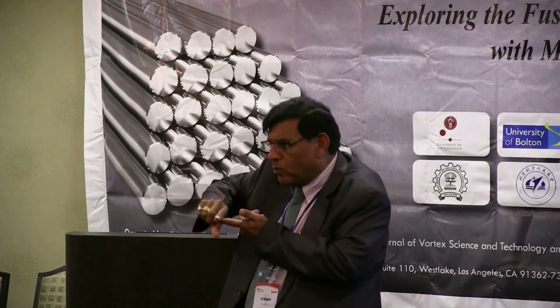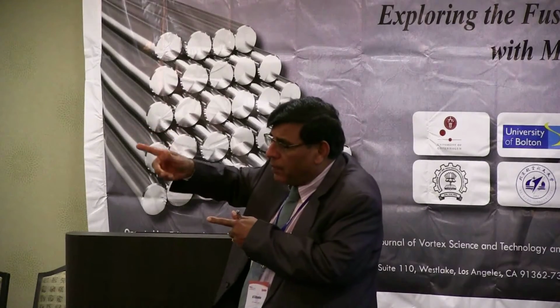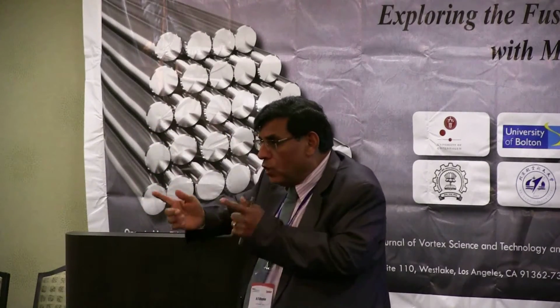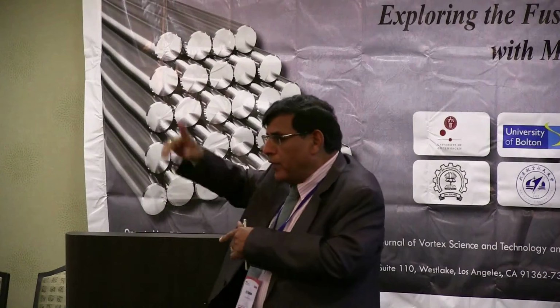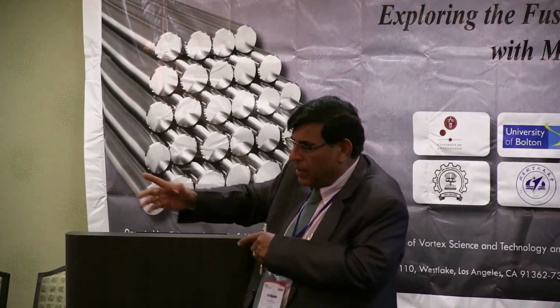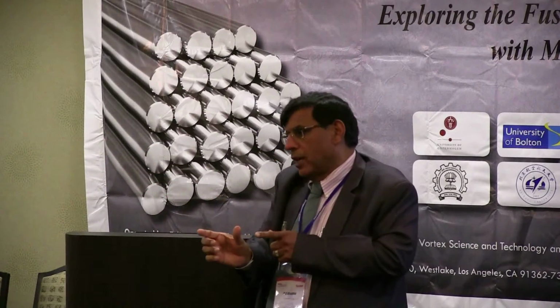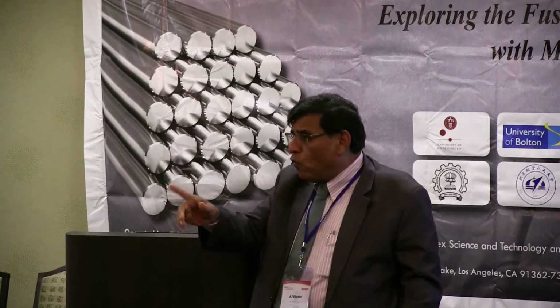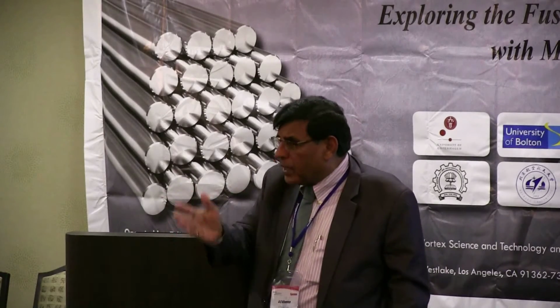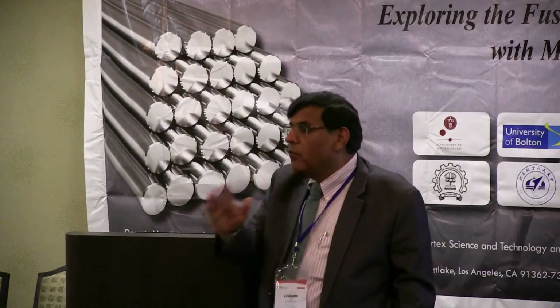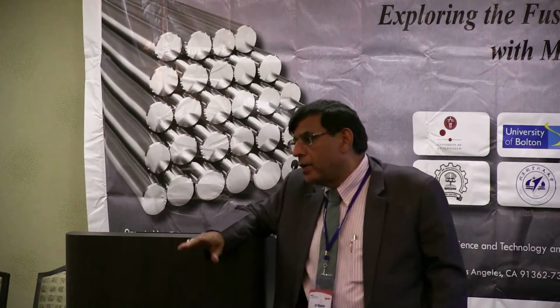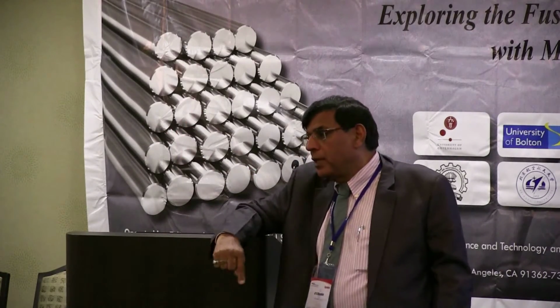different kind of coating onto that. And the third requirement was anti-fog, which we couldn't mix with this. So we are giving them an anti-fog coating separately, and this coating with three things in it. But if you want it on another surface where transparency is not a requirement, we can give you a very strong anti-scratch coating also along with the